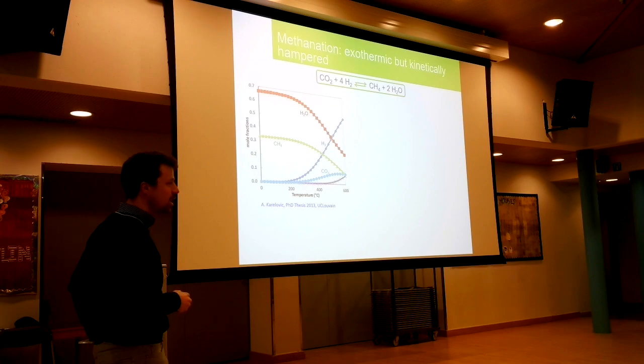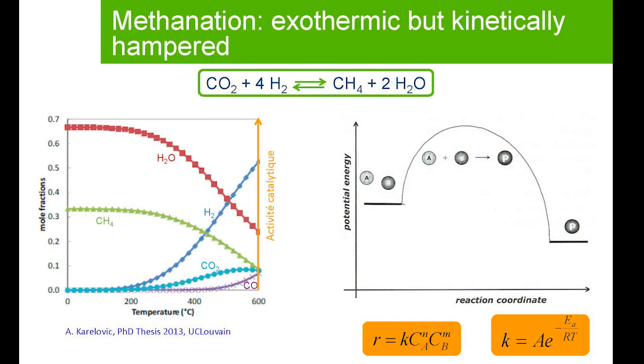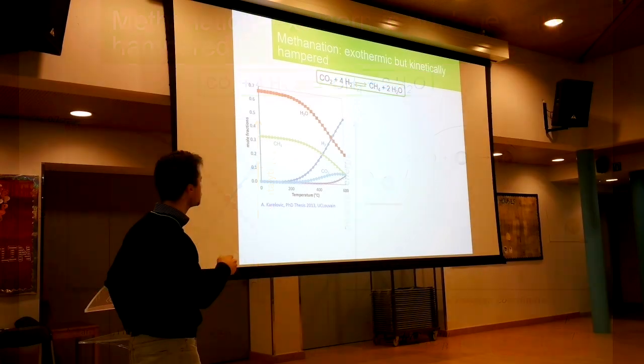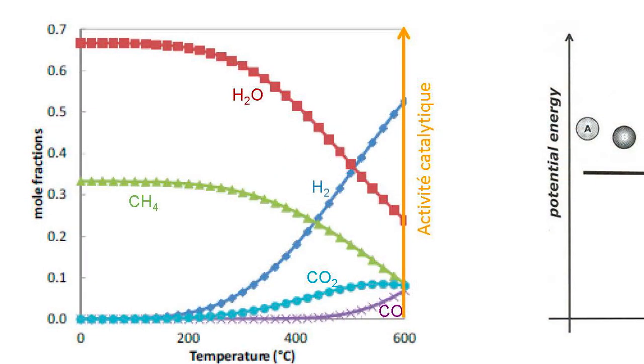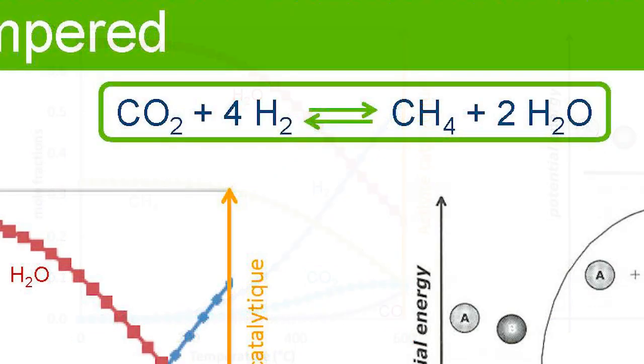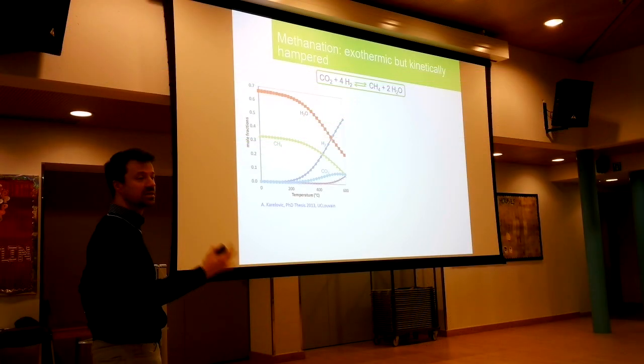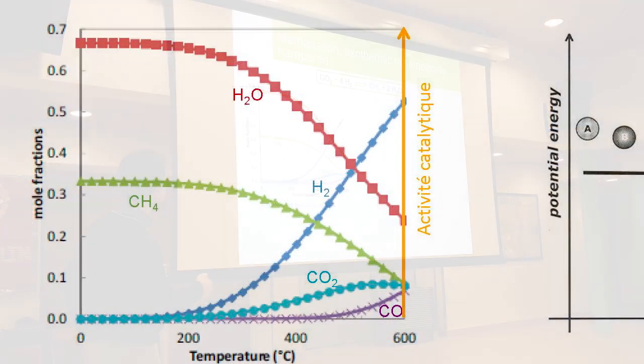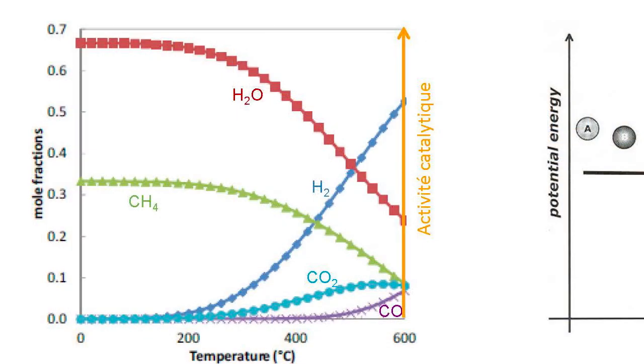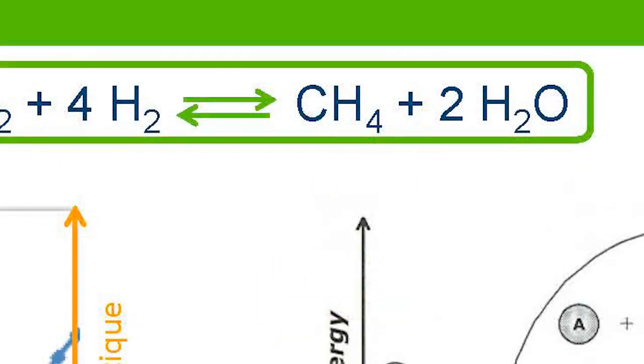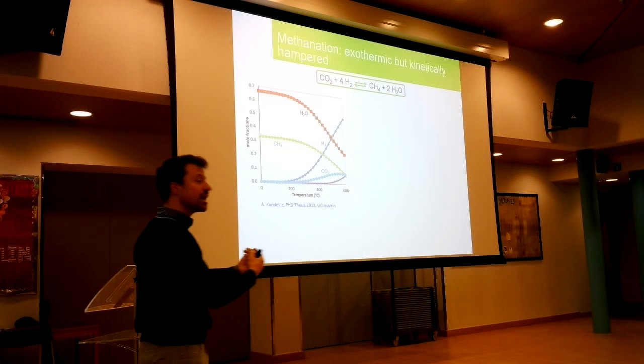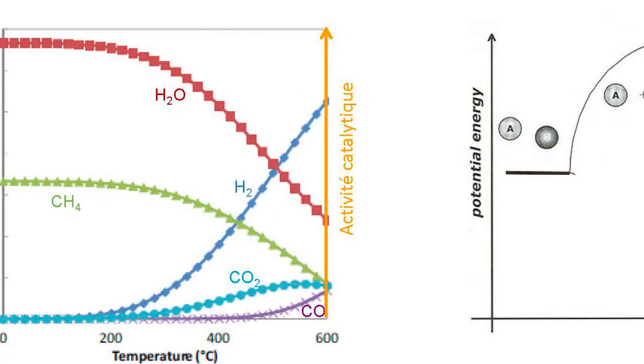Okay, a little bit of thermodynamics. If you look at those molecules, these are the molar fractions at the thermodynamic equilibrium. The methanation reaction, so if you go to the right, is an exothermic reaction, so it's favored at lower temperature. And so you can see that the position of the equilibrium at low temperature here is mostly methane and water, so that side of the equilibrium. So we have to work at relatively low temperature, right? If we go to high temperature, we will have an equilibrium that is less favorable with less methane, okay?